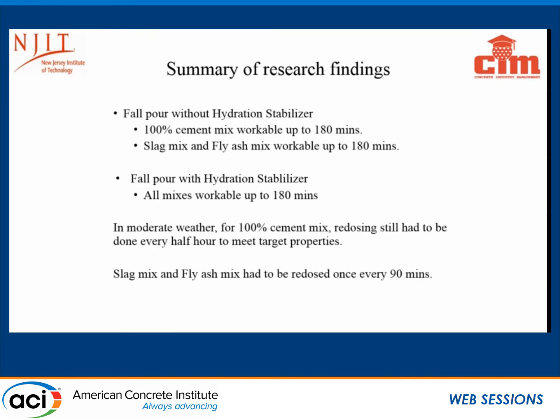Next slide here is a continuation of a summary of the findings. The fall pour without a hydration stabilizer, as you can see, compared to during the summer, we were only able to get up to 100 minutes on the 100% OPC. We were able to get up to 180 minutes without hydration stabilizer in moderate weather. So again, I don't know if that answers some of your question. Fall pour with hydration stabilizer, all the mixes were able to achieve good workability up to 180 minutes.